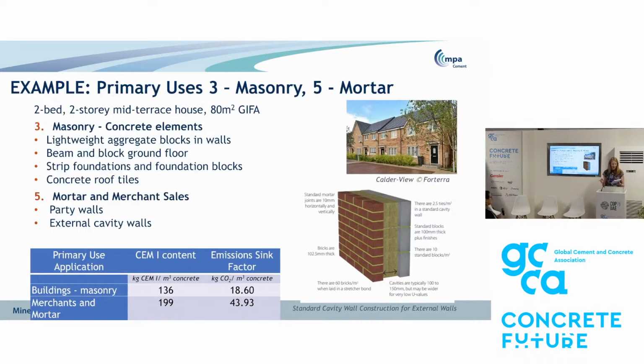So for the lightweight aggregate blocks that are in the external and party walls and the concrete roof tiles, the carbonation front will have progressed through the full depth of those blocks or tiles by the end of the building service life. And when you put all of that together, we find that the CEM I content of the masonry building is about 136 kilograms of CEM I per metre cubed of concrete, and the emission sink factor comes out at 18.6.